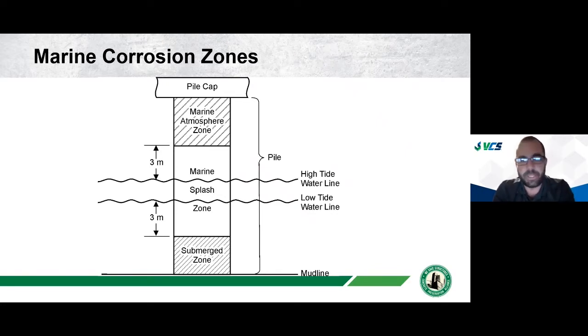I've seen projects where people have put jackets around the marine splash zone, but they did nothing for the submerged zone. And so the corrosion just moved to the submerged zone as opposed to the splash zone. And so the splash zone became the cathode and the submerged became the anode. So, being cautious that, yes, it's submerged. Yes, the corrosion rate will be slower, but will the corrosion rate be zero? No, not necessarily.